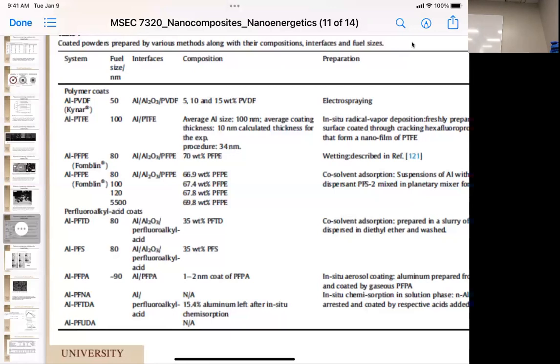Radical vapor deposition on the surface. So you're actually catalyzing the polymerization of tetrafluoroethylene onto the surface there. That was a nice way to do that. Wetting, which is kind of pinky, but the co-solvent adsorption, where you actually have mixtures of solvents, and so one is going to be phase separated out of the solvent onto the solid surface. This is an in situ aerosol coating. So it's kind of like the Electrospray coating, but you're just spraying it and it's drying before it hits the ground. And then a chemical sorption. So they basically are using the natural energy of the aluminum surface to do that.